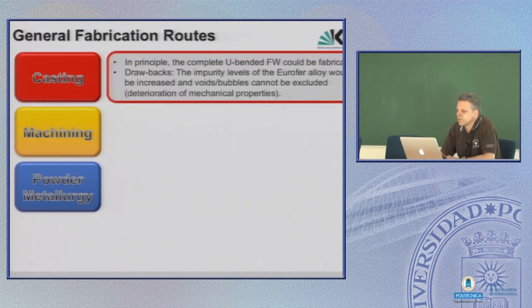For casting, for instance, you could in principle fabricate a complete U-bent first wall. The drawbacks are that in general you have to live with a higher impurity content due to the casting process, and it's also tricky to do this with a Eurofer steel, since 9% chromium steels are not so good for casting. You have to take into account that you will end up with lots of voids or bubbles which are not excluded from the melt. So in general it might be possible, I don't know whether it's really the best process, but in any case you have to take into account that the mechanical properties or material properties would not be as good as before.